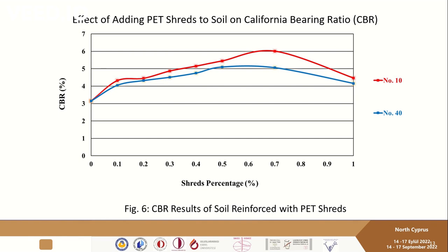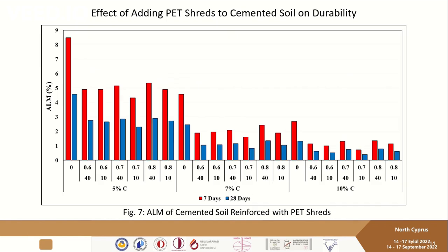If we come to the results, first of all, if we consider the effect of PET shreds addition to the CBR of the soil, we can see that regarding the size and the amount added, the CBR was getting improved by adding PET shreds. But size number 10 proved to be more effective in improving the CBR of the soil, and also the optimum percentage of PET shreds was found to be 0.6, 0.7, and 0.8.